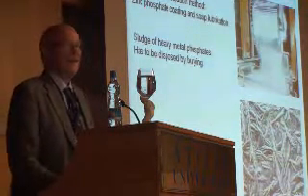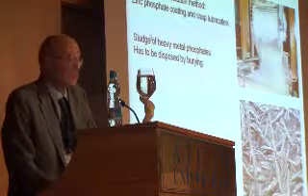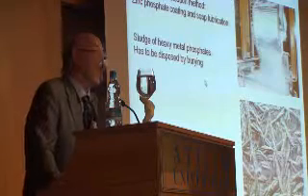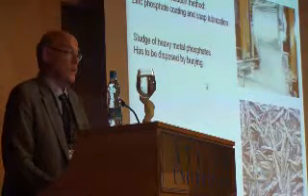I want to say a few words about lubricants for cold forging, because I think there are some cold forgers here. And there has been quite interesting development in the latest years regarding cold forging lubricants. In cold forging, you also have environmental problems using zinc phosphate coatings, which gives sludge of heavy metal phosphates which have to be disposed by burying, and it's costly to renovate your baths and so on. It's also a lengthy procedure, and all these things have motivated lubricant manufacturers to try and find alternatives. And there are many alternatives which are not working especially well, but work for lighter cold forging operations.